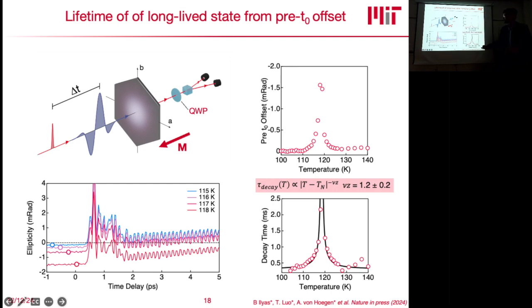What we could do is just shift it up, and this would give you the correct time, but it would diminish the information about the pre-time zero signal. But is this pre-time zero effect stronger at higher temperature? It is, yeah. It diverges here at the critical temperature. So this is 118 Kelvin. You can see it is pretty sizable, and then above the critical temperature, it completely disappears again.